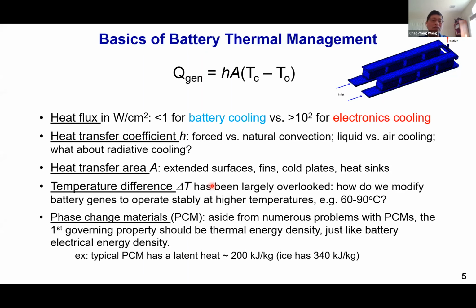If you take a typical PCM like a wax, it usually has a latent heat of about 200 kilojoules per kilogram. And if you convert it into watt hours, dividing by a factor of 3.6, that boils down to about 55 watt hour per kg. Now this can be compared to the energy density of lithium-ion batteries, where we talk about 200 to 300 watt hour per kg. So immediately we know those PCM materials have very, very low energy density, probably 5 to 6 times lower than lithium-ion batteries. And you would always want to think whether or not you want to use something that is low energy density, which means heavier and bulkier materials, to do thermal management. So that's something I want to mention to the community as well.